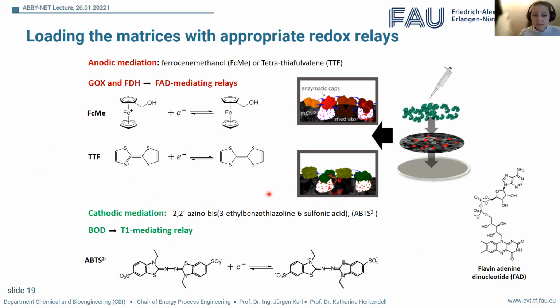Both of these had the positive characteristic that their redox potential is very close to that of glucose oxidase or fructose dehydrogenase, specifically the FAD active center, meaning we didn't lose a lot of electromotive force. Now, for the cathodic mediation, we had the oxygen reduction catalyzed by the bilirubin oxidase, and we used a well-known and well-described mediator in the scientific literature called ABTS.